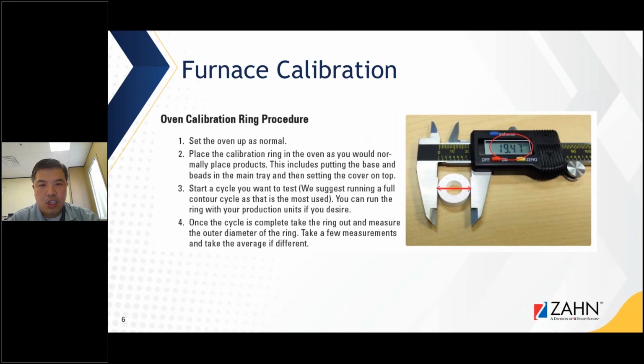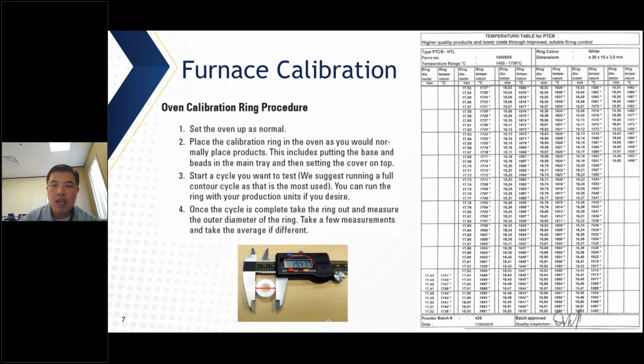Okay, so on this chart right here, on a small chart on the side, you'll see the different percentages of how much a ring shrinks, and with that shrinkage, it allows you to know what kind of temperature it's been set on. Okay, so if the temperature is firing too high or too low, your zirconia will not get a true shade of your zirconia, especially with Zirlux transition. It is very, very critical that we are at the right temperature and know what we have